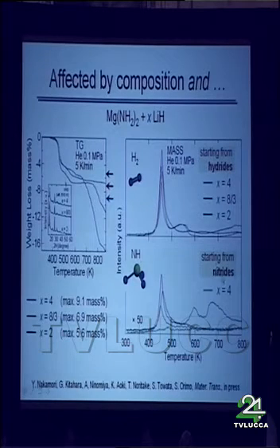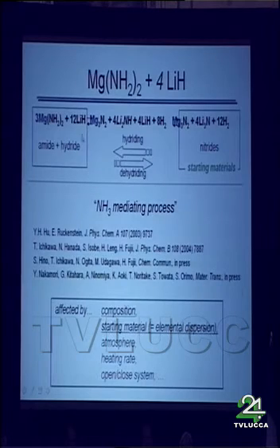In case of specific samples, we can very much suppress the ammonia formation. This combination, the magnesium amide and lithium hydride, can be formed just by the hydrogenation of the mixture of nitride. In that case, I simply guess that elemental dispersion is good enough not to form ammonia so much.